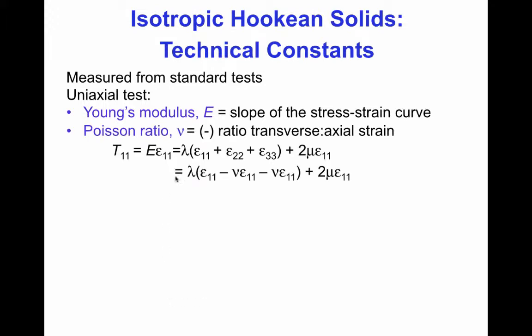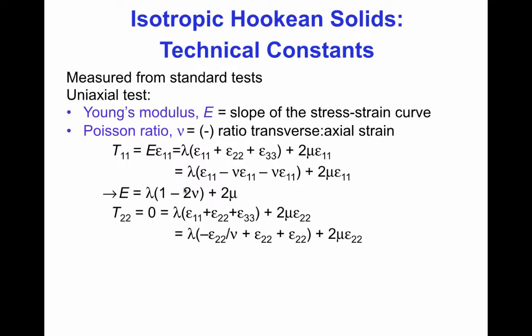The Poisson ratio nu is the negative of the ratio of the transverse to longitudinal (axial) strain. So if you strain the material by 1% and it shrinks by 0.3%, the Poisson ratio is 0.3. We evaluate the Cauchy stress in the x1 direction and equate it to E times the Cauchy strain in the same direction for an isotropic Hookean elastic solid under uniaxial tension. That gives E times epsilon_11 equals lambda times (epsilon_11 plus epsilon_22 plus epsilon_33) plus 2 mu times epsilon_11. Using the definition of Poisson ratio, epsilon_22 and epsilon_33 are minus nu times epsilon_11.